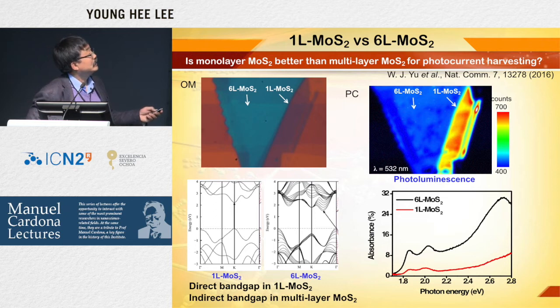But also very small luminescence from 6 layer. This is opposite because if you consider 6 layer, of course, more absorbance, definitely you see more absorbance, right? So you would expect a higher photoluminescence from this, but apparently it is not. This is because of the direct band transition versus indirect band transition. This is bulk. This is monolayer, so the photoluminescence quantum efficiency, of course, definitely improved.